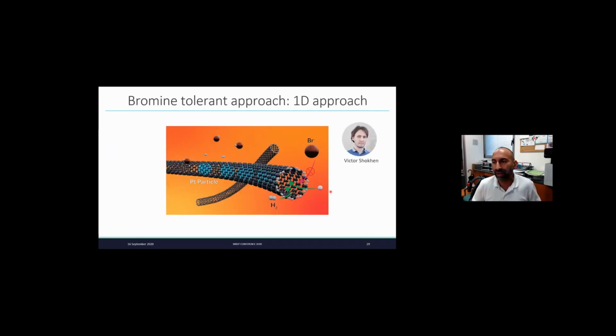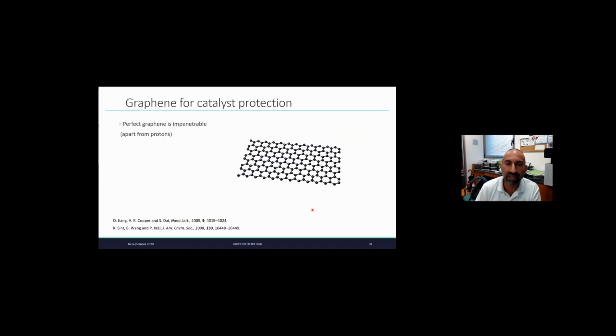So we try to do another approach, which is to encapsulate the platinum inside carbon nanotubes. Carbon nanotubes are well known. They should also improve the loading of the catalyst because we can use a very small amount of platinum. And if we can encapsulate the platinum inside, then we would be able to also confine the reaction and block the bromine. So Victor Shokhen did the nice cartoon that you see here, and also some of the experiment that you're going to see. But this work is mainly the work of Sam Ardisti.